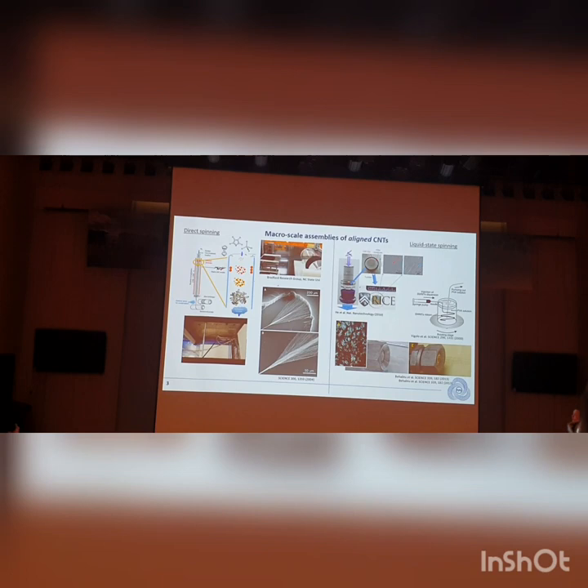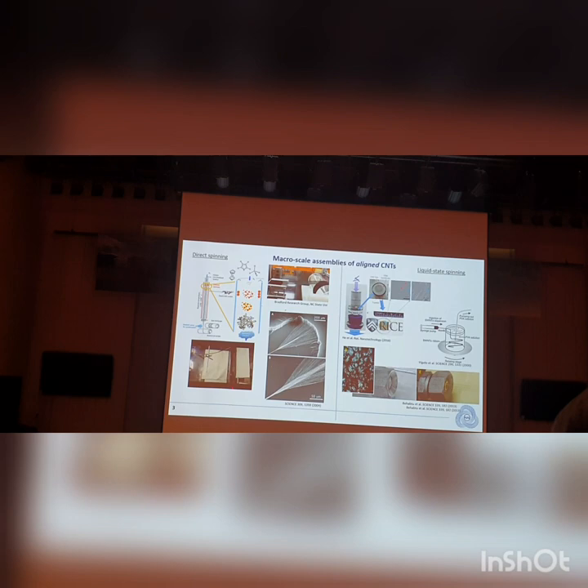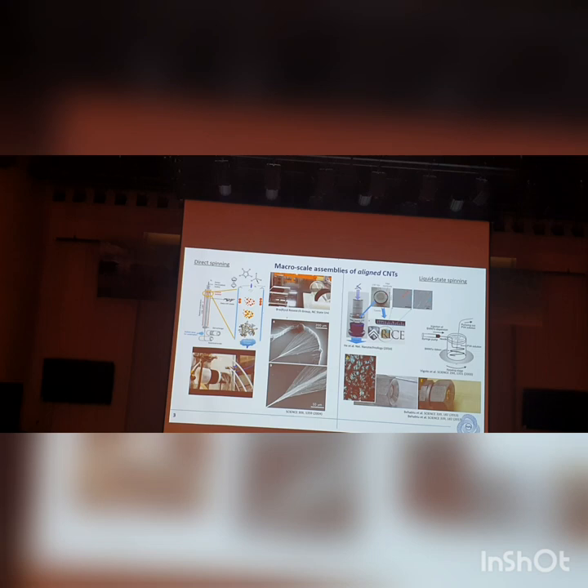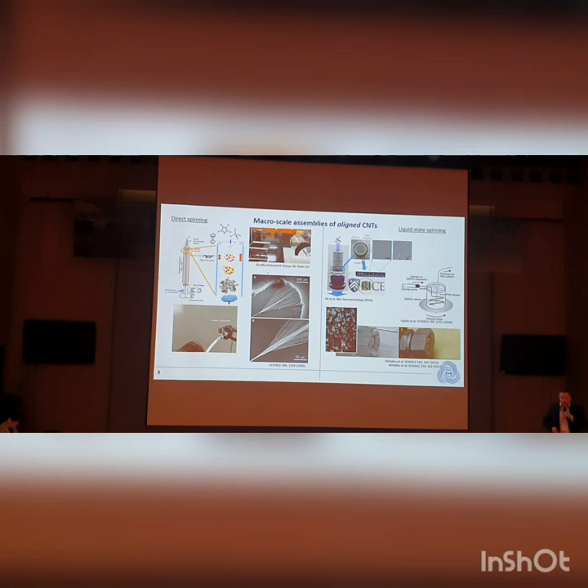There are lots of ways to affect alignment of CNTs. In our case, direct spinning is a little difficult because we're spinning from a dilute aerosol in the gas phase — we've played with changing the winding rate and gas flow rate, but there aren't many knobs to tune. Spinning from forests gives a bit more control. The nicest techniques are liquid-state spinning: coagulation spinning and acid spinning. Spinning from a gel or liquid crystalline mesophase gives a lot of control over alignment, which is why wet-spun fibers generally have slightly better as-received properties than dry-spun fibers.